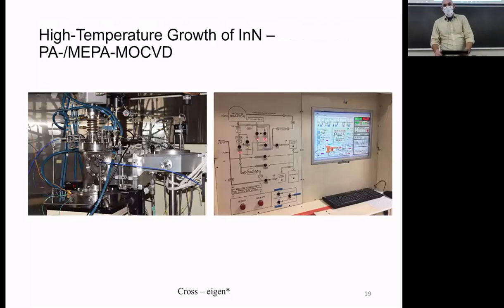So what we did was we had a second reactor that we've been working on since about 2015 again. This reactor was a plasma-enhanced or migration-enhanced plasma-assisted MOCVD reactor. So again, metal organic chemical vapor deposition. But on top of that, we used a plasma source instead of using other materials.